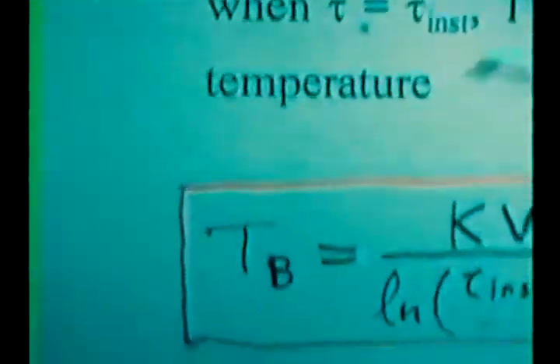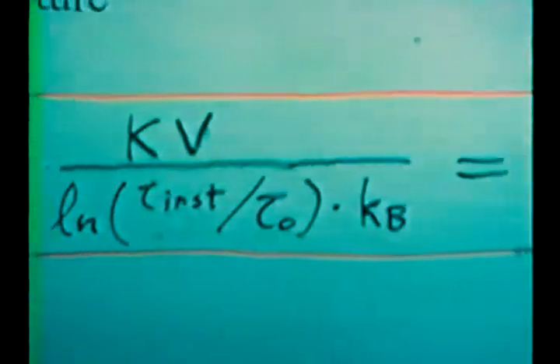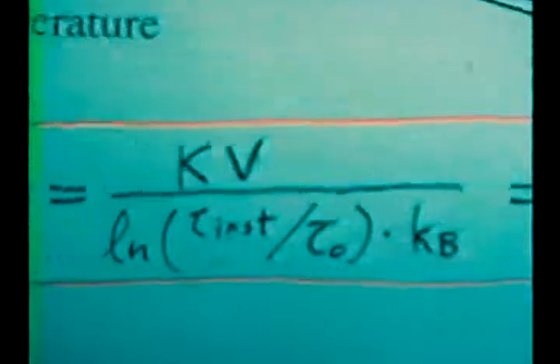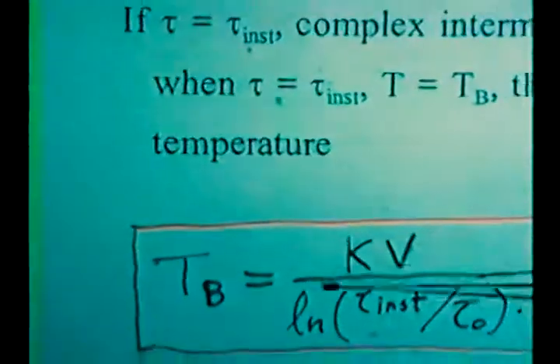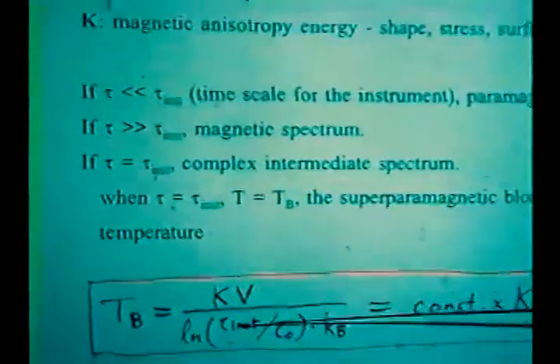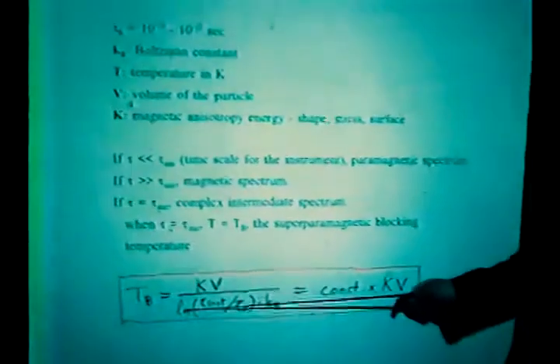And we define this temperature as TB, and we call it the blocking temperature. The blocking temperature, if I convert this equation, I get this equation, and these are constants. So the blocking temperature is proportional to K, the magnetic anisotropic energy, and the volume.